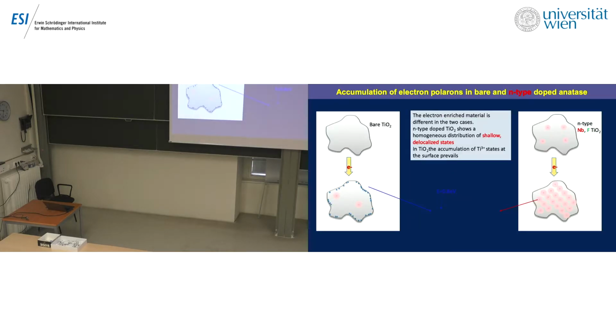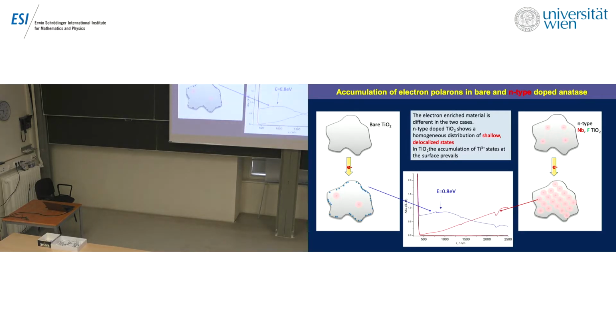So this is the final slide, okay? And so 2 types of messages in pristine or bare titanium dioxide. You go by reduction or by irradiation to this kind of situation: few polarons in the bulk, delocalized polaron, and many things at the surface. But if you start from this situation of enriched material, you obtain a much more uniform material. And there is another proof of this, and this is the optical absorption. The optical absorption is dramatically different in the 2 cases. There is a broad absorption, but the maximum is here, 0.8 electron volt. And in this other case, the maximum is in the infrared. So we are talking about very different states, narrow states, etc. So I have finished my talk.